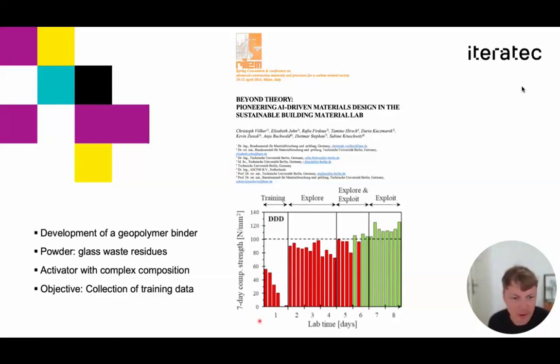In this study, we were aiming to develop a geopolymer binder formulation that exceeded the 100 megapascal strength after 7 days. So we wanted to maximize the compressive strength of this material. We did this in 8 consecutive rounds where we collected data and trained a machine learning model to improve the suggestions in the next round and find a good material after some time. And as you can see, we were successful, especially at the end. We were able to find multiple formulations that exceeded our threshold.